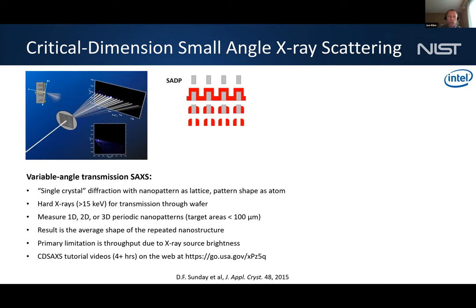And so for an example of it, with making features smaller and smaller before EUV worked, they had to develop some tricks to be able to make smaller features. And so this is spacer-assisted double patterning, where you can create a structure using conventional immersion lithography, and you do ALD to deposit a conformal film. And then you can do a directional etch, and it essentially just removes the material from the bottom and the top of the line, and it leaves the sidewalls there. And so then you remove the original structure that you have, and now you have something with half the pitch of what you started with.